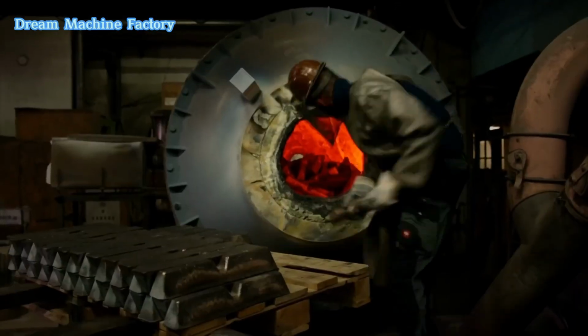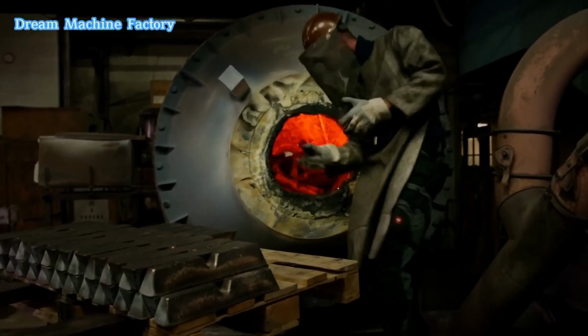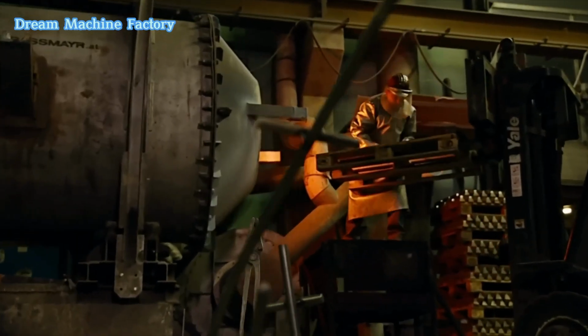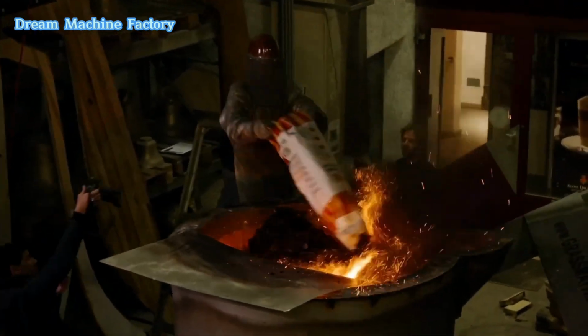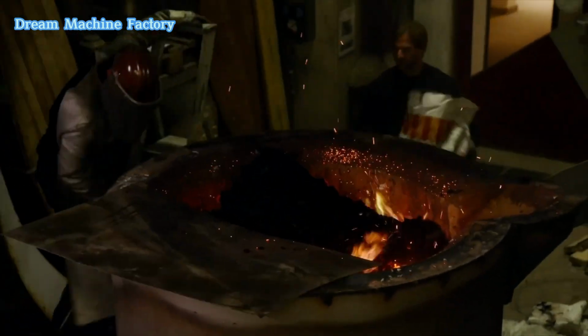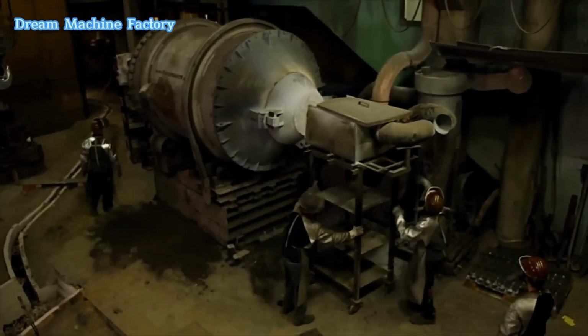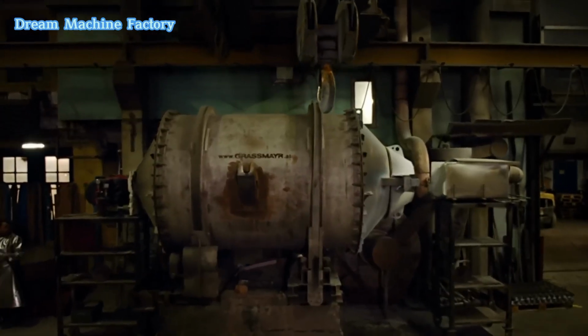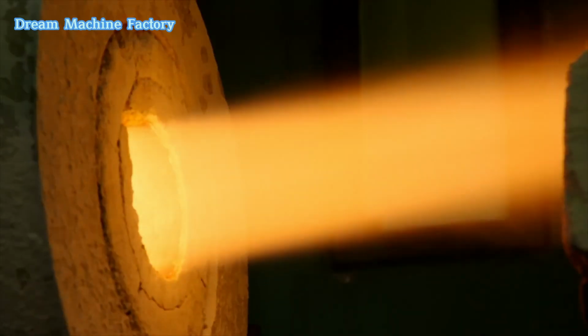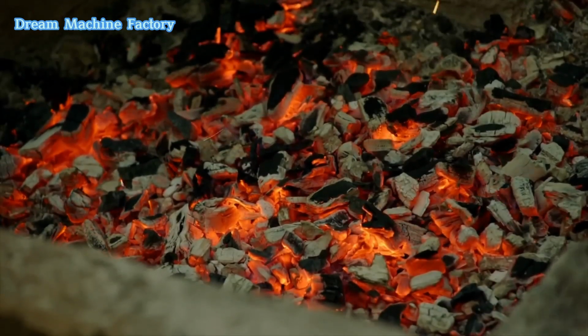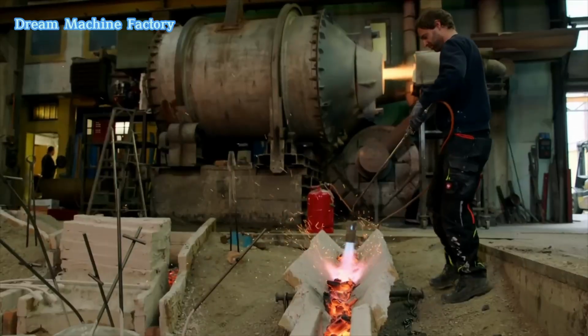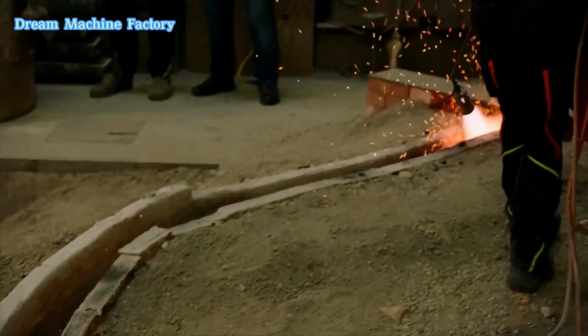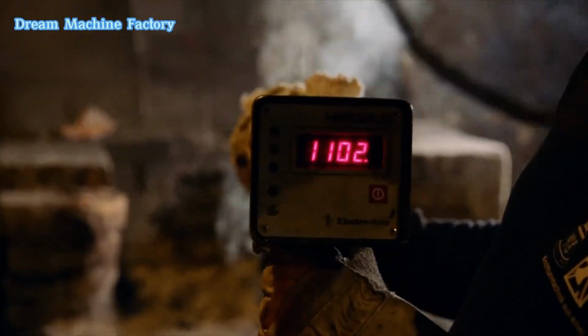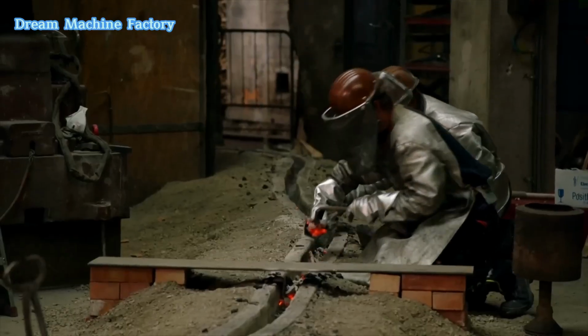Casting is one of the most critical stages in bell making. The molten bronze is carefully poured into the preheated mold in a slow and controlled manner to prevent defects such as air pockets or weak spots. This process requires years of expertise, as any error could ruin the entire bell. Once the mold is filled, the bell is left to cool for several days. The gradual cooling process is crucial to prevent internal stresses and ensure uniform metal structure. Rushing this step could lead to cracks or warping, compromising the bell's integrity.